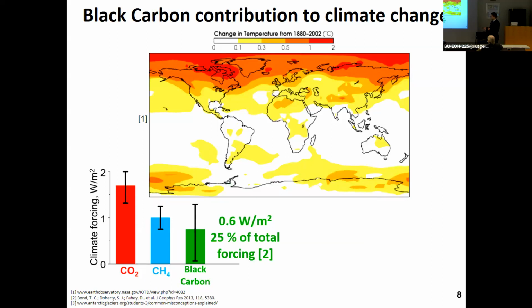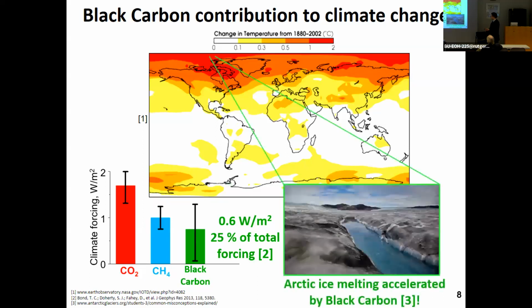So black carbon, of course, contributes to global warming either through the radiative forcing or, for example, as you can see over here in the Arctic, by deposition on the ice, on the glaciers. Here is actually a rather recent picture of the Arctic ice that is melting, and its melting is accelerated significantly by deposition of black carbon nanoparticles on the ice. And this is quite relevant, even for the United States over here, as most of these nanoparticles are emitted by ships that are cruising around this area over here. So it's really important to quantify, first of all, accurately the contribution of black carbon to global warming, and then come up with policies that can help us mitigate its impact on our environment and, of course, public health.